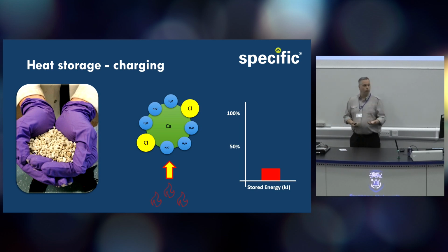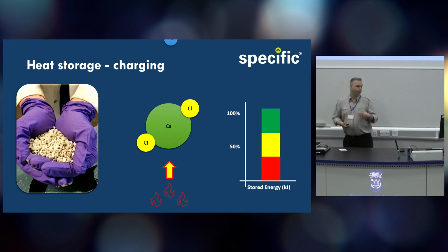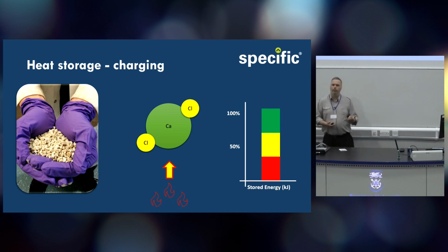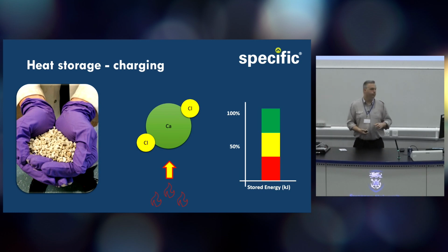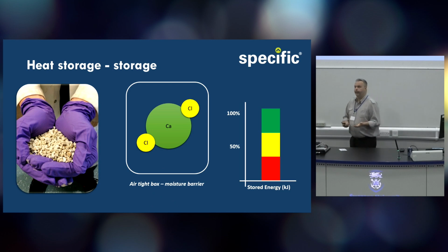If we apply a hot air stream to that, perhaps a waste energy stream, we have the thermal interaction between the bonds. The bonds break and remove the moisture away in the airstream, and it's an endothermic reaction, so all the energy required to break those bonds is then stored chemically within the material. We can then encase that in an airtight box. In the case of our demonstration systems, this will be a hermetically sealed steel box or aluminium box or something like that. In our labs, it's more about Tupperware, but whichever way you do it, it's very simple to do and prevents any energy leakage from these materials.